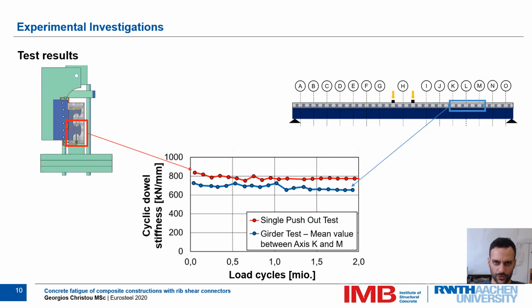By means of the elongations measured over the height of the girder, the shear force per dowel was now calculated, and considering the slip in the interconnection, it is possible to calculate the cyclic dowel stiffness of the dowels and compare them to the stiffness of the single push-out tests. Once again, we have a very good agreement between the single push-out test and the girder test. The roughly constant cyclic stiffness in combination with the roughly constant elastic slip in the interconnection suggests a constant loading over the lifespan of the girder as soon as the first fatigue phase is completed.